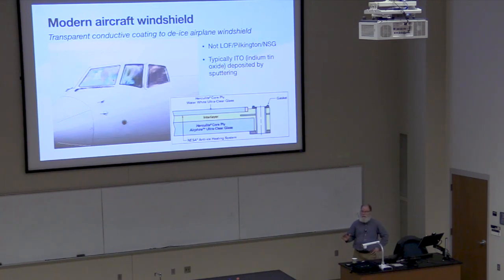Now that doesn't matter in transmission to the pilots because the amount of light reflected from the inside is a lot less than the amount coming through the window. So they don't see it. It doesn't affect their vision. And that glass is not made by us. That's not our product. That is typically a different TCO material, indium tin oxide, deposited by a different process.